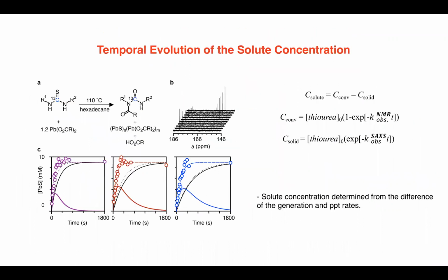All right, so in these same experiments, we went about measuring the conversion kinetics independently. Brendan McMurtry, who just graduated, made carbon-13 labeled ureas and monitored their decomposition to this N-oleoyl urea byproduct. You can see that in the C13 spectrum here. There's the urea in A, and there's an N-oleoyl urea product here. And so these kinetics give us a direct measure of the solute production.